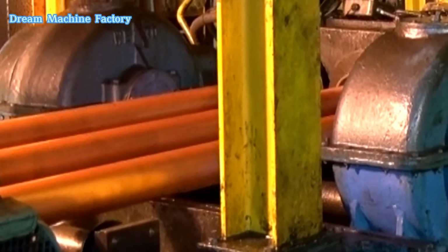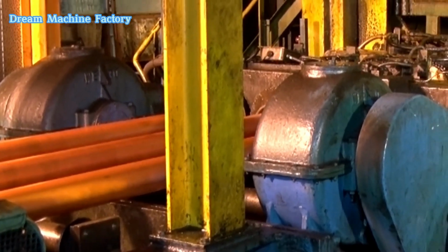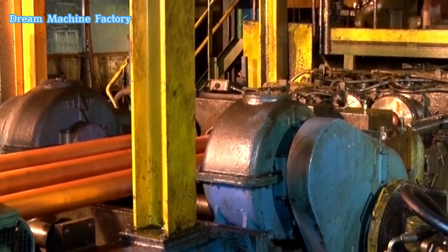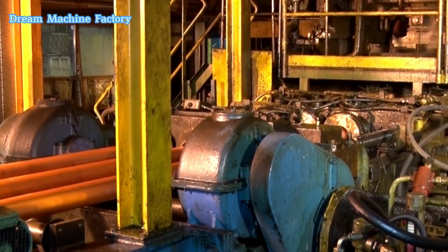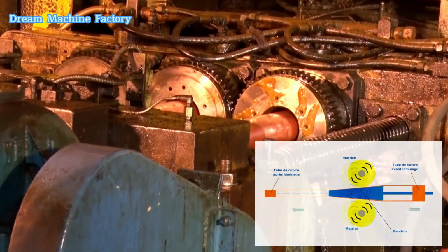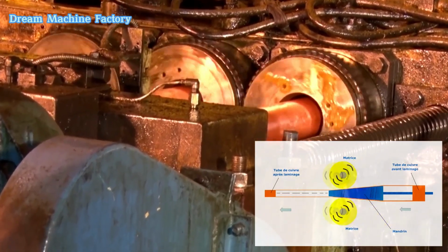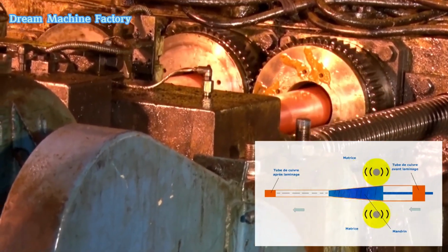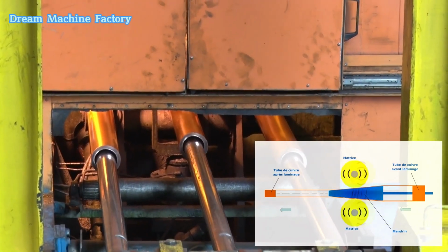Tubes are straightened and cut into specific lengths or wound into coils. If coils are required to be flexible, they are annealed, heated in a furnace at around 450 degrees Celsius to restore malleability. After cooling, the coils are wrapped in plastic film for protection and packaging.